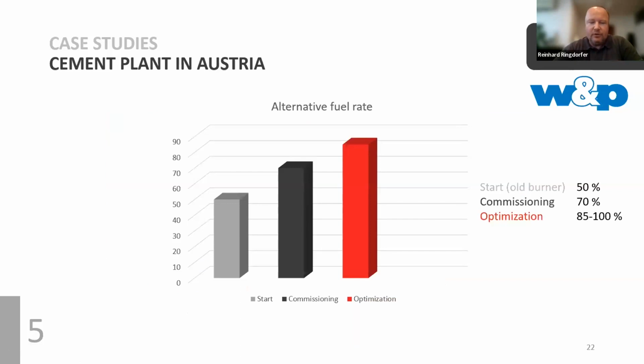So the commissioning of the burner was done, and the 70% were immediately reached. And after optimization, the substitution rate at the moment is somewhere between 85 and 100%. For your information, the 100% is because the plant is now running at lower than design capacity. So they are allowed to fire 100% because they have a certain limit. If they're running at full capacity, they go over this limit of what they can fire at the moment. But at lower capacity, they can go up to 100% secondary fuel firing. So they are using only fluff at the main burner.